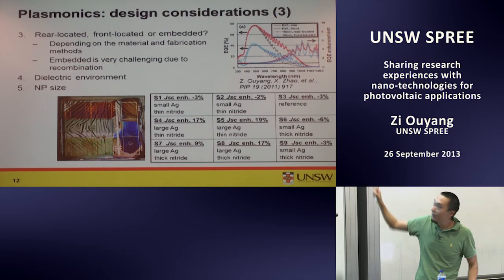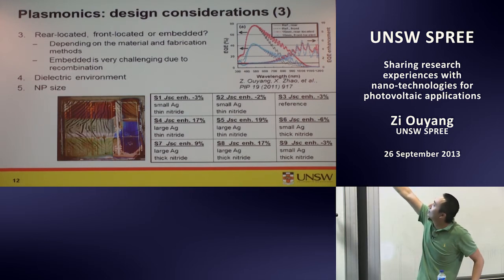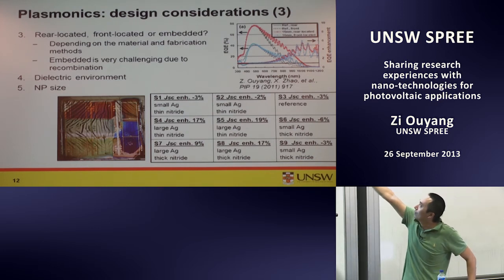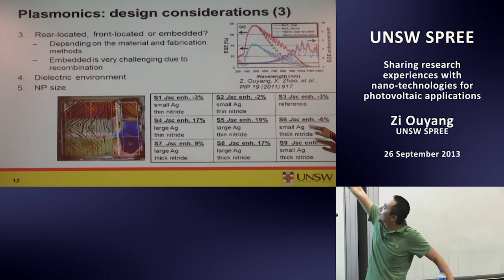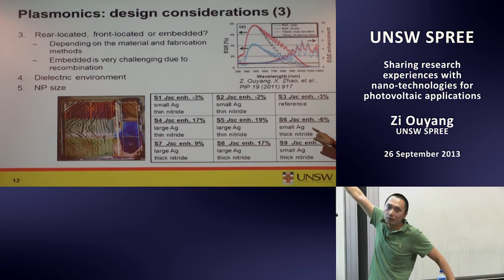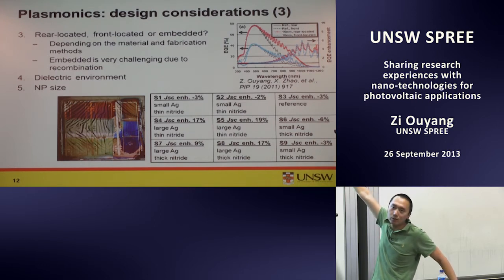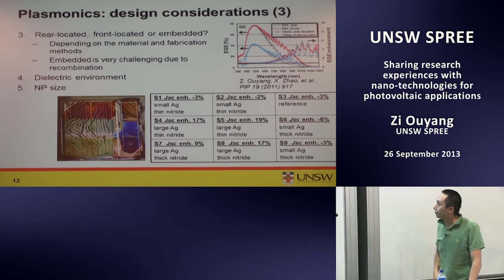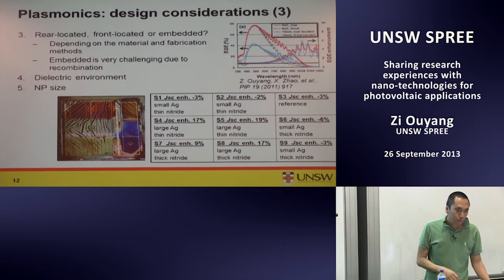The figure on the upper right-hand side is the comparison between the front located nanoparticles and the rear located ones, and the reference is the black curve. You see both have enhancement, but for the front located one, if we look at the lower curves, at 300 to 400 nanometers you have a dip. That dip can kill the performance if you put it on the front side. But if you put it on the rear side, you don't have that problem, because short wavelength light just cannot go through. So that's good.